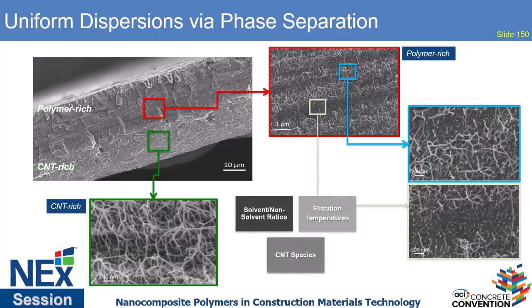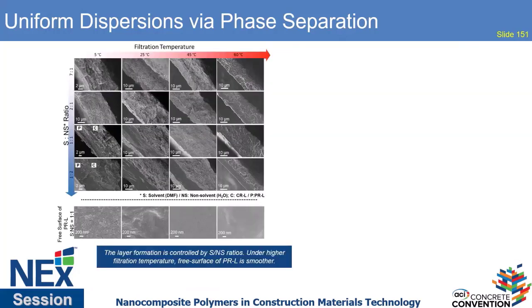So we've been looking at this as a means of trying to capture the polymer or the nanomaterial we want to use in a particular polymer matrix as a better way of dispersing these materials as opposed to just adding more and more loading into the system. So we studied this in detail and we looked at a lot of different temperatures, non-solvent, solvent mixtures, a lot of different conditions to try to understand it.